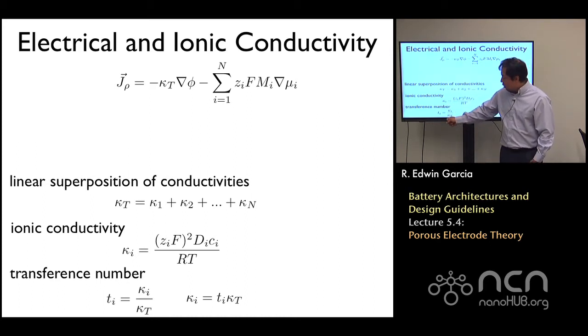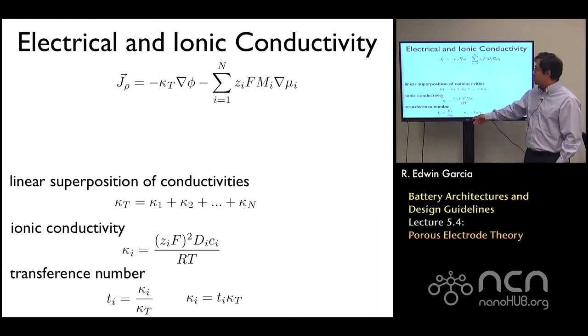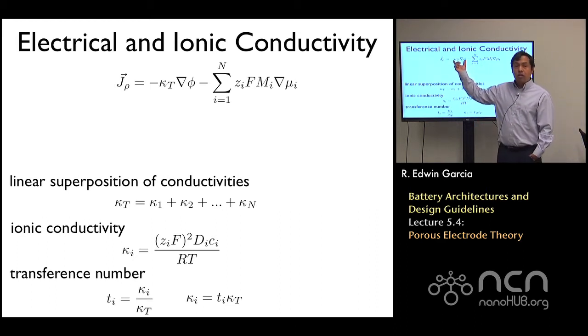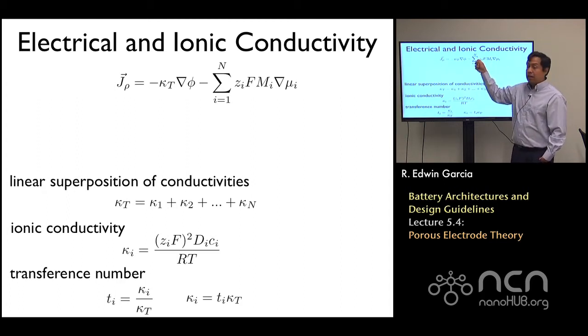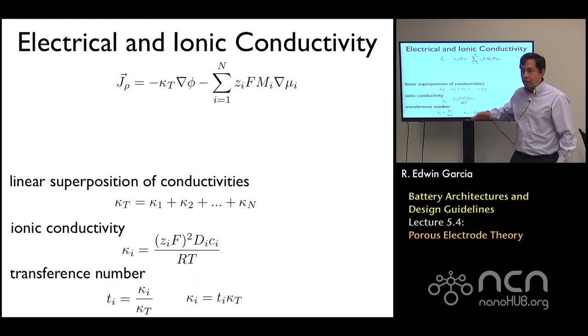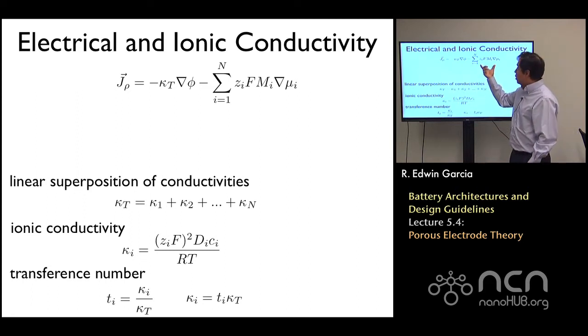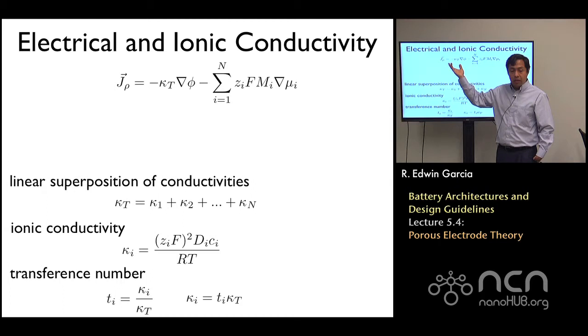And based on that, you can define effectively the transference number as the ratio of the contribution to the conductivity divided by the total conductivity of the system. So the effective charge would really be a function of how these species are flowing in different directions, and how the chemical contributions are either driving it back if Z sub i is positive, or driving it forward if Z sub i is negative, right? It really depends on the sign of this, and it can accelerate or favor transport from one side to the other, or it can really try to slow it down to the point of completely stopping it.